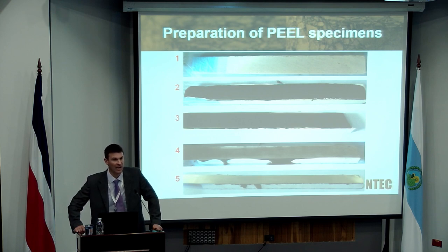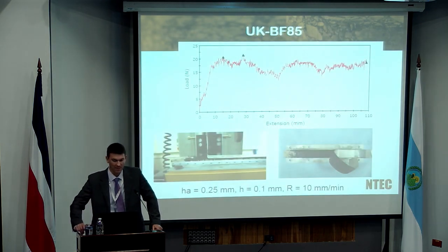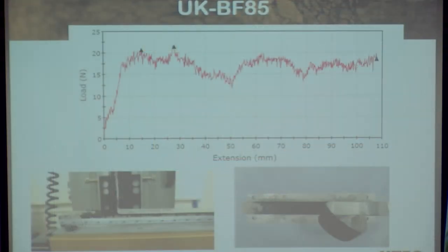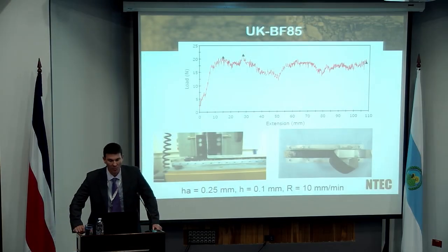But basically, make sure your aluminium strip sticks to your adhesive bitumen, cool down the entire system, and then you are ready for testing. And the testing is done by very accurately peeling off that aluminium top plate. And we use a 90-degree peel test. So although the peel test can be done at any angle you like, if you use 90 degrees, then your displacement rate in the vertical plane is exactly the same as your displacement rate in the horizontal plane. It makes the calculations a lot easier to work out your displacement rate and how you work out your fracture energies. So with a 90-degree peel arm, there are testing issues, but once you've solved that, it's a lot easier and a lot cleaner in terms of the mathematics.